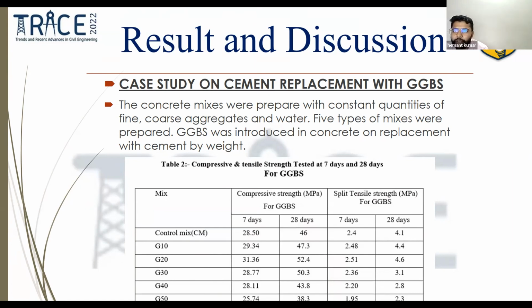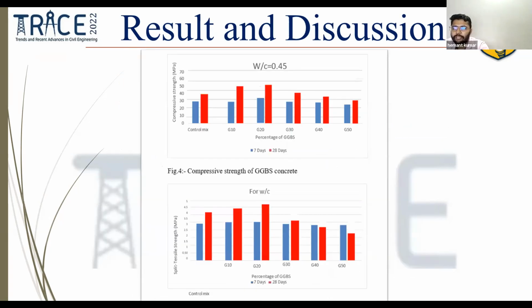GGBS was introduced in concrete as replacement of cement by weight. Here we prepare five mixtures by varying the percentage of cement and GGBS: G10, G20, G30, G40, and G50, and we get this strength. These are the table and charts which are showing the results. At G20, we get the highest compressive strength and tensile strength on 7 and 28 days.